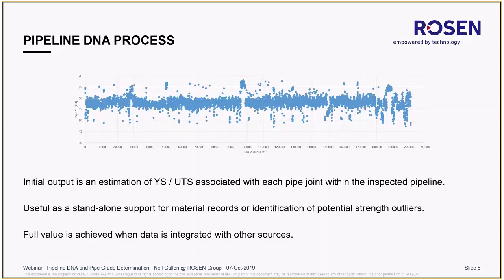And apologies for the units, but we've done quite a bit of work in the US, so we have to work in feet and KSI as well as normal units. And you can see there that this average yield strength of the pipe is somewhere between 55 and 60 KSI. So that is what, about 400 MPa. Each of those points identifies an individual joint, and you can see there is a broad consistency down the length, but there are also some outliers. There are some areas of apparently higher yield strength, and there are some areas of apparently lower yield strength.